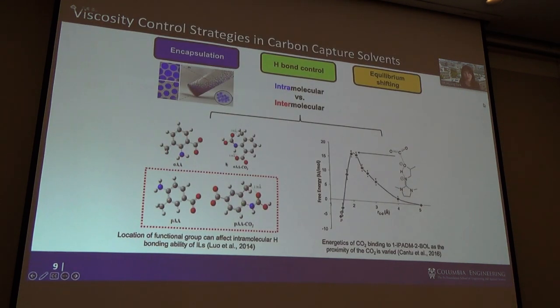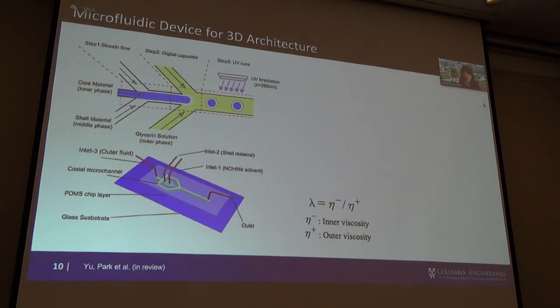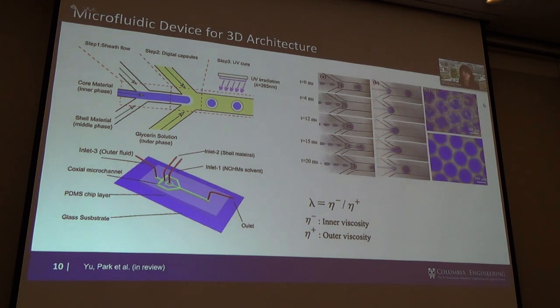Maybe one of the methods can be encapsulation. It's as if you have a very honey-like consistency liquid, we can chop them apart and keep them apart. So we started thinking about this area, and the first generation we made was using a microfluidic device. The blue liquid is our NOILs material, and the white liquid is the UV curable polymer. By creating a droplet inside a droplet and then UV curing only the shell material and letting that be gas permeable, we were able to produce materials like this.